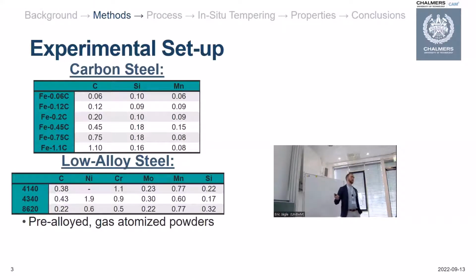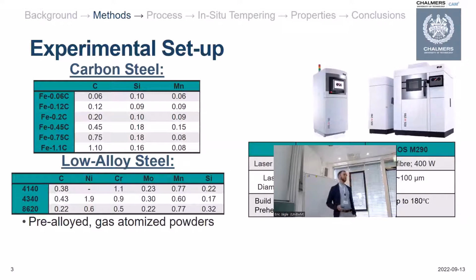Now, to produce these specimens, we used 2 different machines. The first was an EOS M100 machine, which we used for initial process development of both the carbon and low alloy steel powders. We also had an EOS M290 machine, which we used for secondary process development for the low alloy steels, as well as the production of the mechanical property specimens. And there are some differences between the machines, but the major one we focused on was that the M290 allowed us to preheat the build plate up to 180 degrees Celsius.